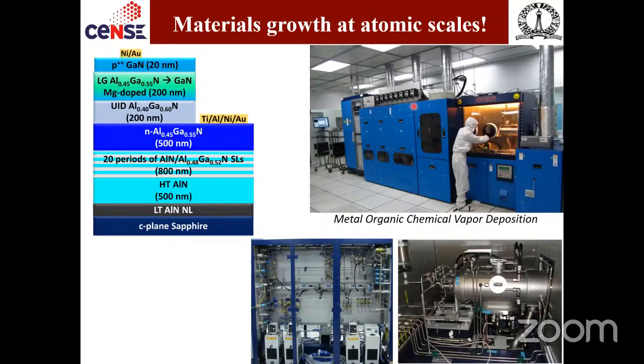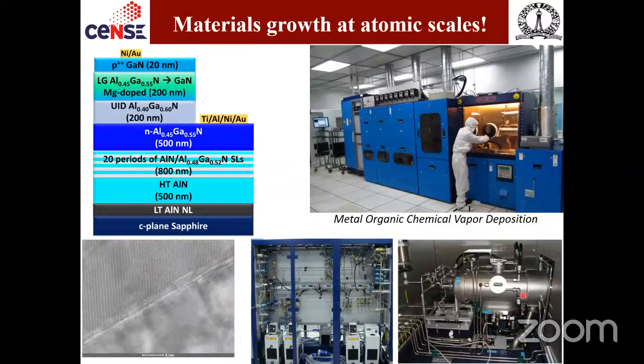And the reactor operates at elevated temperatures such as 1200 or 1300 degrees Celsius, which is a crazy high temperature by any normal standard. But we have to go to such high temperatures to synthesize these semiconductor materials and let the chemistry do its trick. So eventually we end up with very nice looking materials if we optimize all the parameters involved.